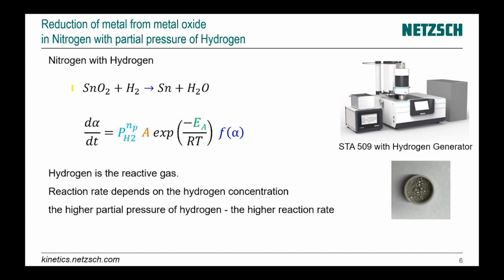Here for our kinetics, we have the metal oxide with hydrogen, where we have a pure metal and water. If the concentration of hydrogen is higher, so if the partial pressure of hydrogen is higher, then the reaction rate will be higher. Here we have the kinetic equation where the partial pressure of hydrogen is before the pre-exponential factor, and here we have the activation energy, which depends on the chemical nature of our material and will not be changed because of the partial pressure.